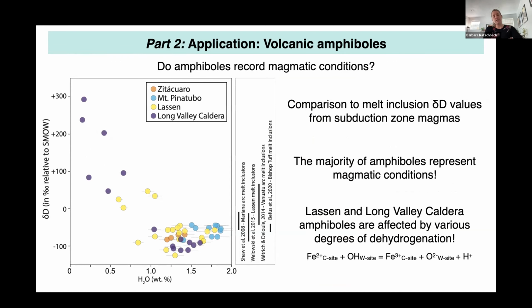So now we figured out that some grains from Lassen and Long Valley potentially experienced dehydrogenation and associated oxidation of iron after crystallization from a magma. But how do we know that the majority of grains which plot in this narrow range are actually representing magmatic conditions? That can be evaluated if we compare amphibole hydrogen isotope composition to the hydrogen isotope composition of melt inclusions, which basically directly reflect the composition of the magma. And this is shown here. Those are a couple of published studies looking into the hydrogen isotope composition of typical subduction zone magmas. And you can see that the majority of amphiboles actually overlap with those estimates. So we think that they really represent magmatic conditions and have not been modified after crystallization.